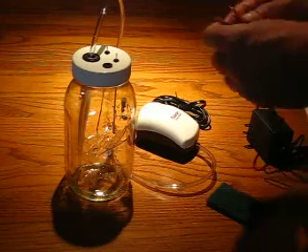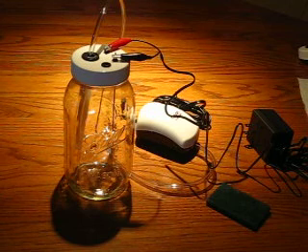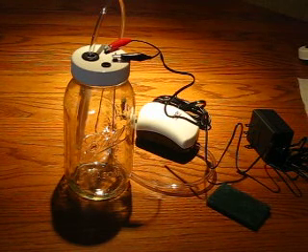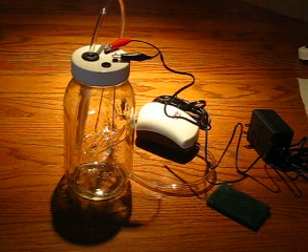Then take your alligator clips from your transformer — by the way, this is a 12 volt transformer. My recommendation is that 12 volts requires roughly four and a half hours of production time to create a nanoparticle colloidal silver with roughly 25 parts per million in relative silver content. There's a lot of controversy over parts per million. We use parts per million based on what a total dissolved solids meter can read, which in effect is not truly colloidal, but we use that process in our work.